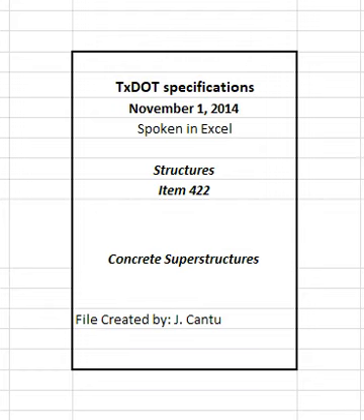4.1.7 Placing bridge rails. Reinforcing steel and concrete for bridge rails may be placed on bridge slabs once the slab concrete has attained a compressive strength of 3000 psi. Ensure the slab concrete has attained its design strength specified in Section 421.4.1, Classification of Concrete Mix Designs, before placing railing concrete if slip-forming methods are used for railing concrete.